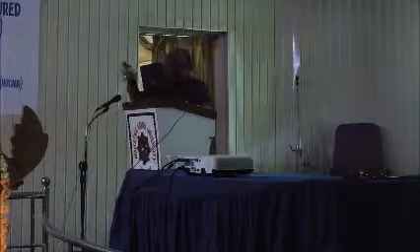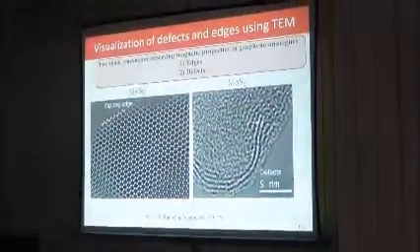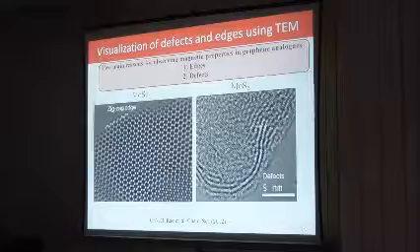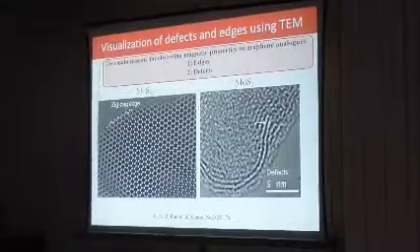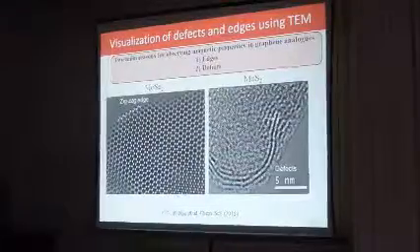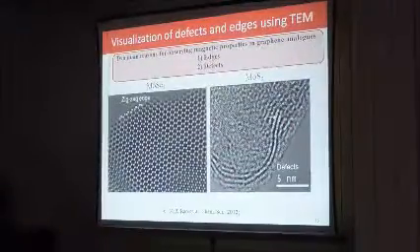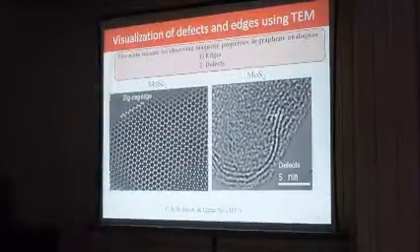If you remember, graphene is known to show weak ferromagnetism because of edge effects and defects. Same with MoS2 sheets, they show weak ferromagnetism. And again, because of the edges, I showed you the zigzag edges of graphene. Just like the zigzag edges of graphene, zigzag edges in MoS2, MoSe2, or the defects in these materials are responsible for the weak ferromagnetism.